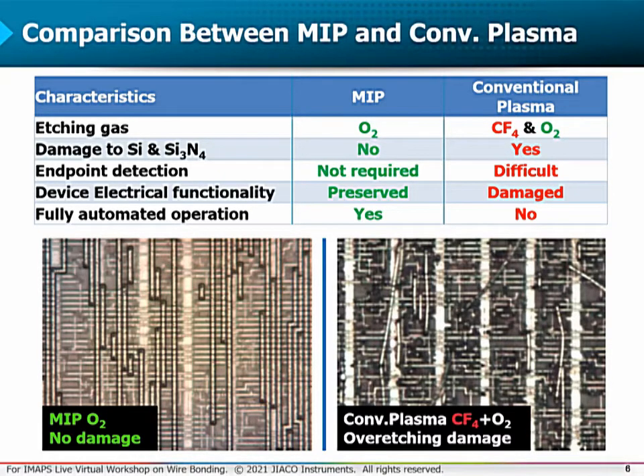Again, conventional plasma decapsulation is a highly uncontrollable process with a low selectivity, and due to that, it is very difficult to implement endpoint detection. On the other hand, the MIP process is just a gentle oxygen etching and does not require endpoint detection. MIP will preserve electrical functionality of decapsulated devices, unlike conventional plasma. Another important difference is that MIP has a fully automated operation, in a sense that etching and cleaning steps are conducted automatically, as will be shown in a few slides.